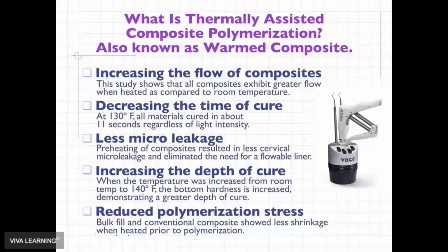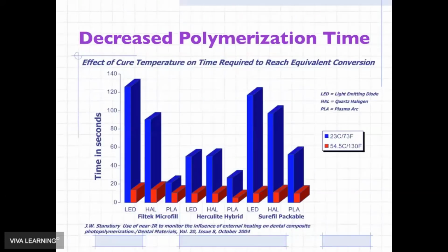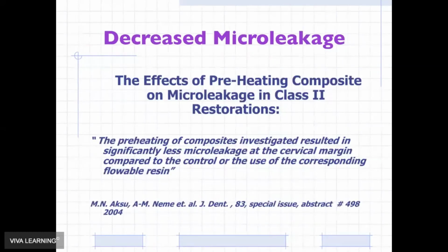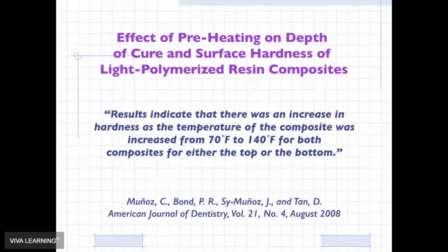Now, if we go over the literature, this is not anecdotal. If you look at the benefits of composite warming: decreasing the cure time, increasing the flow, less microleakage, increasing the depth of cure, and reduced polymerization stress and shrinkage. This is not anecdotal, this is evidence-based, because you can see from these bar graphs, not mine, that the literature does support the effects of preheating the composite on microleakage. And this is what I go for, evidence-based science. And you can see here, Carlos Munoz, the surface hardness is better and increases as you heat the composite.